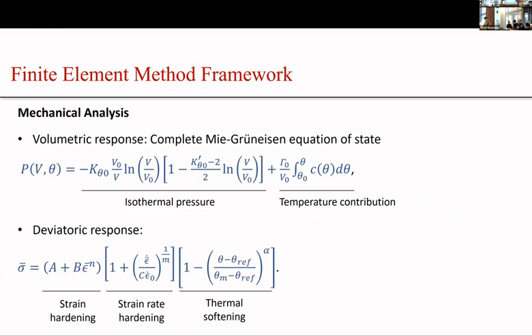So in the simulation, we did a fully coupled thermal mechanical analysis. For the mechanical part, the volumetric response is modeled through the complete Mie-Grüneisen equation of state, where the theta in this equation represents the temperature. The first term is the isothermal pressure as a function of volume, and the second term represents the pressure increase due to temperature rise. The K theta naught and the K prime theta naught in the equation represent the bulk modulus and its pressure derivative at ambient state. For the deviatoric or the hardening part, this is the hardening equation that we used, which incorporates a power law strain hardening, a Cowper-Symonds type of strain rate hardening, and also thermal softening.